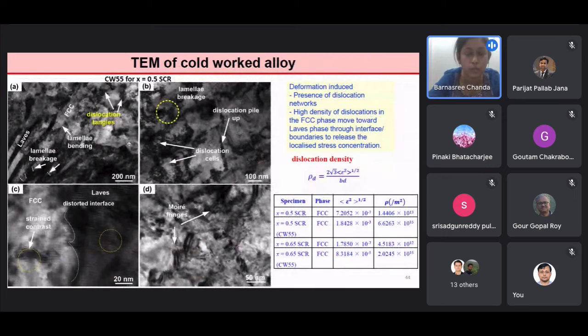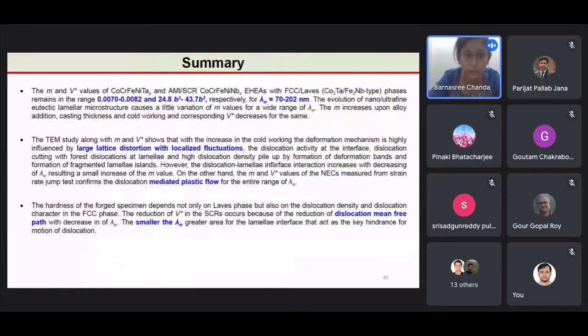Further, the transmission electron microscopy of the highly deformed sample, that is 55% 0.5 SCR, shows a high density of dislocation in the FCC phase, and the presence of dislocation tangles, lamellae bending, lamellae breakage, dislocation pileup, and a highly distorted interface can be seen. And when we measure the dislocation density, we see that the dislocation density in case of the FCC phase increases by an order of magnitude when we deform the sample up to 55%.